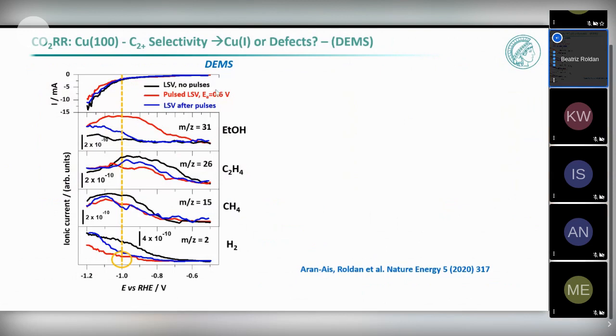So if you look with differential electrochemical mass spectroscopy at these 3 samples, we are going to see very clear changes. So in red is the rough sample where we have also copper plus coexisting with metallic copper. We see here ethanol formation, and we see a very low onset potential for the ethanol formation. The blue curve here corresponds to the ethanol that we are making in the rough surface, but it's only metallic. And here, this is the surface where we didn't pulse. So ethanol is clearly suppressed.